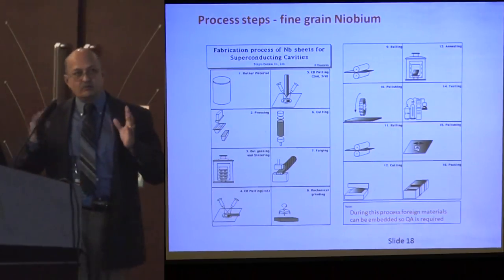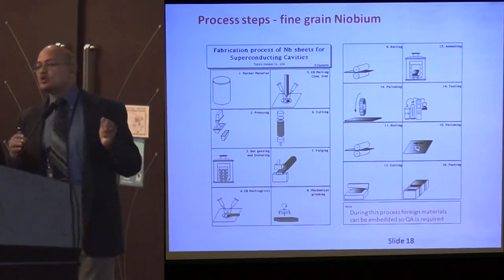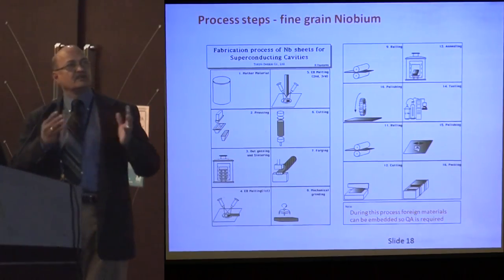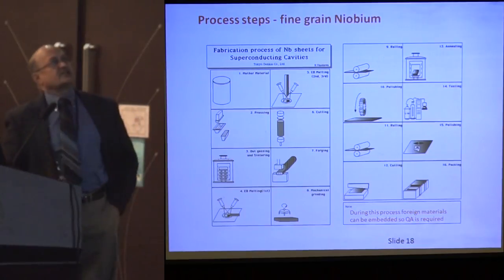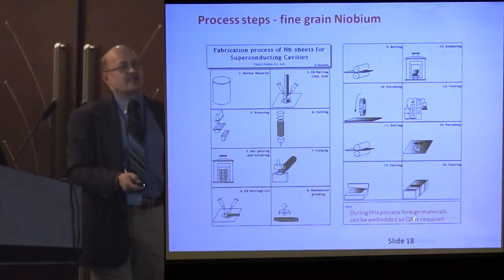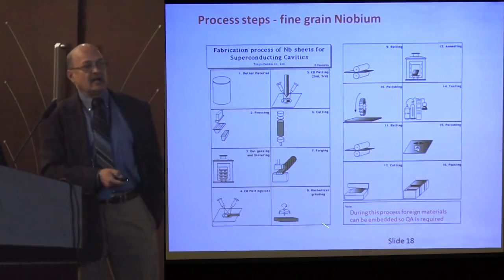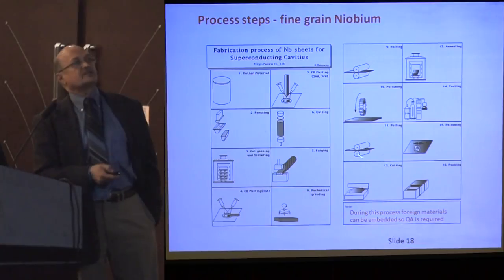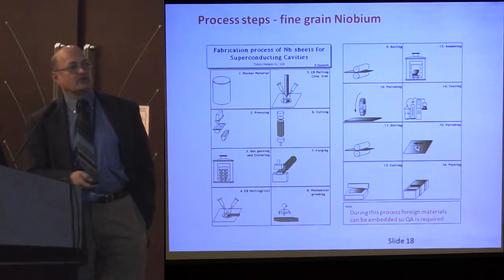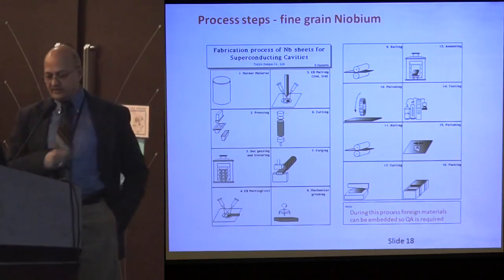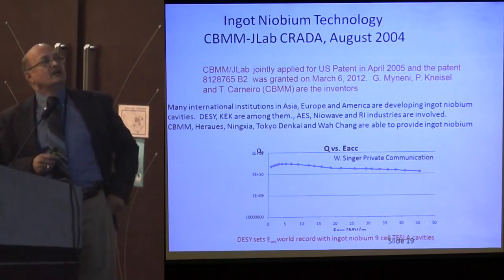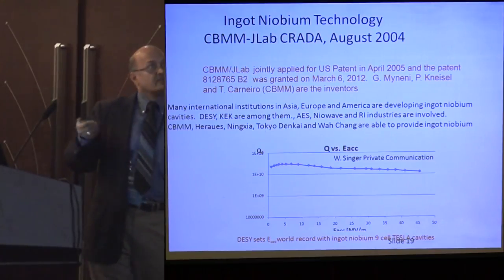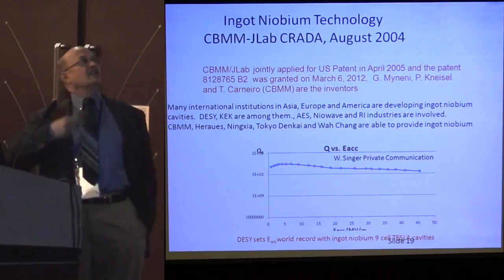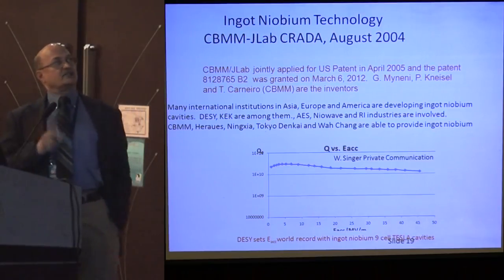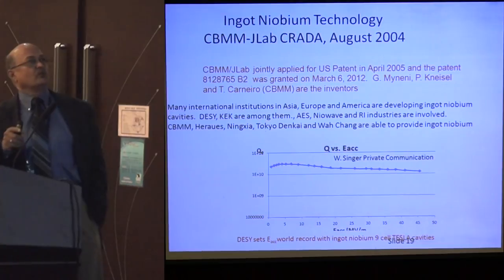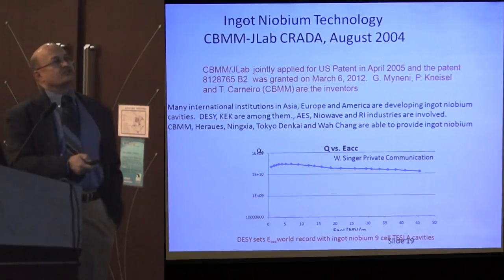As I said, the current practice is to use fine-grained niobium sheet so that you can form the cavity half cells, and this is the process used for that. During this process, it is possible to have inclusions of hardened materials in the steps of this rolling or any of these steps, so QA is required. As a result, the cost of this niobium is pretty high. So in 2004, CBMM and JLab started collaborating to understand the specification requirements for this niobium, why it should be so low.